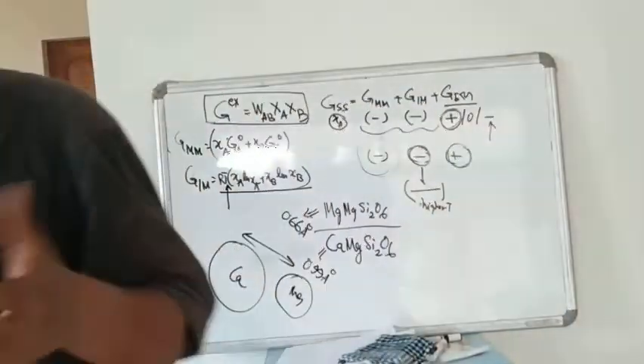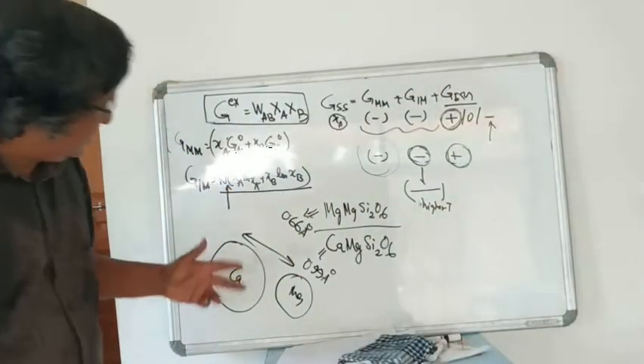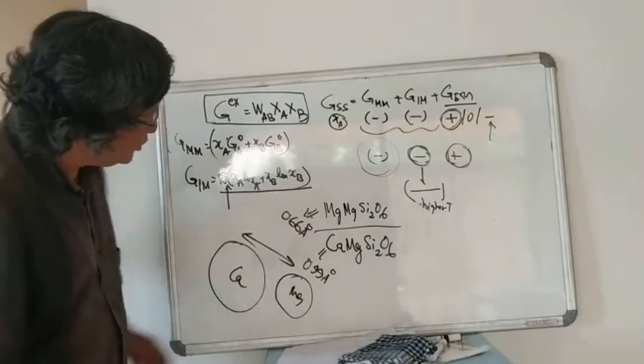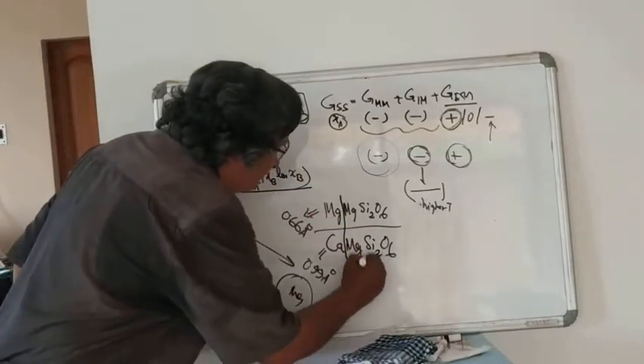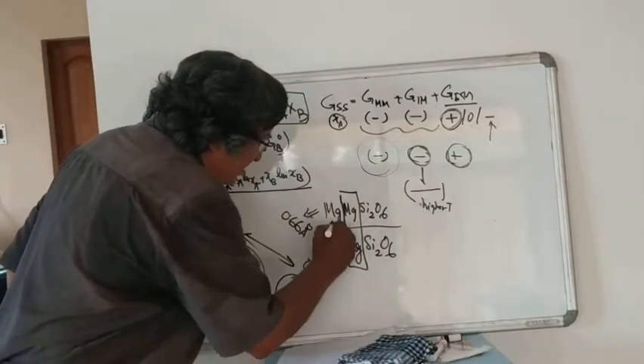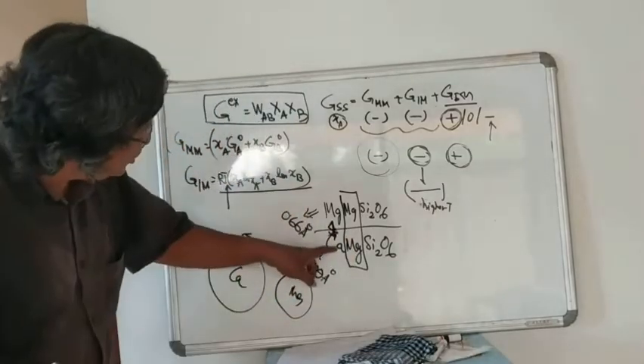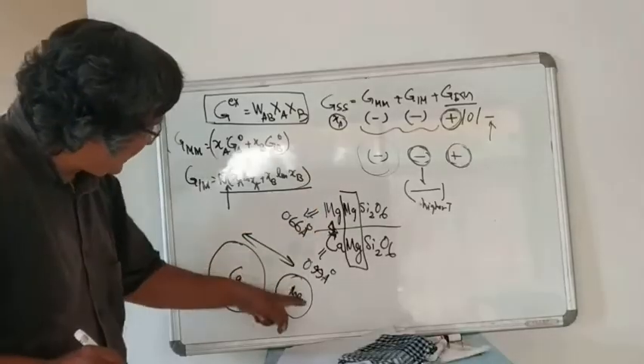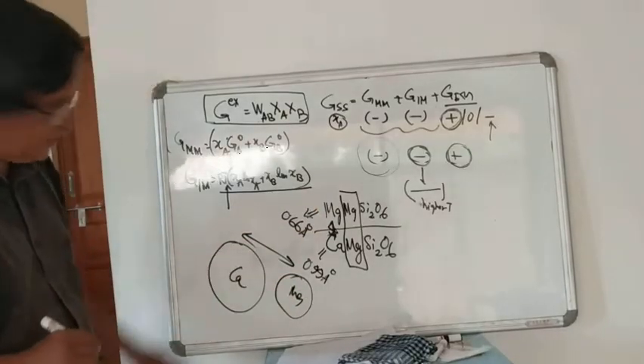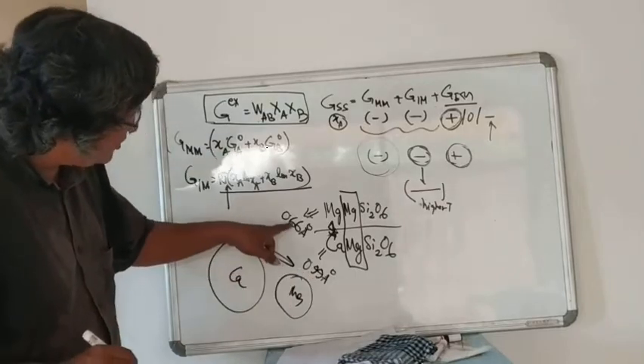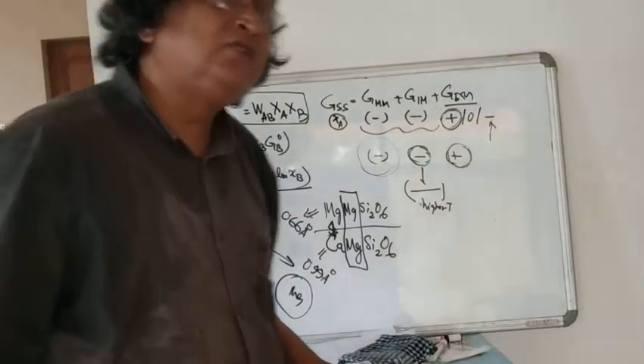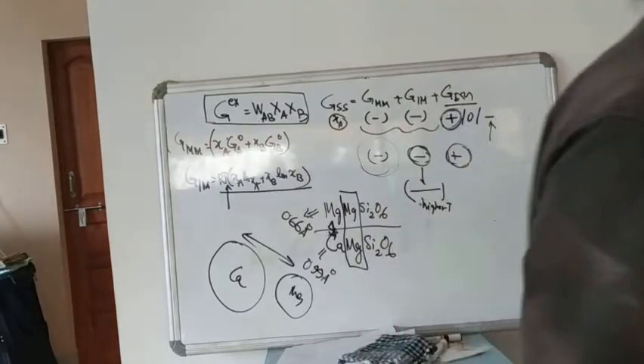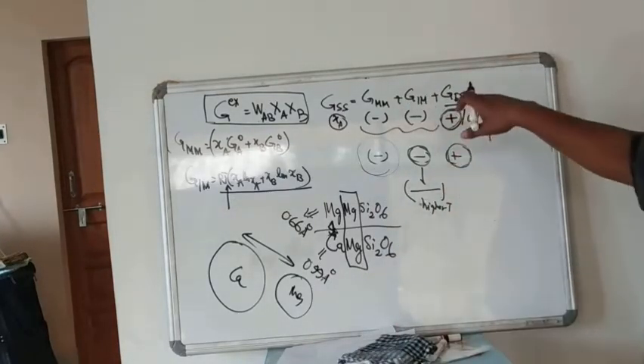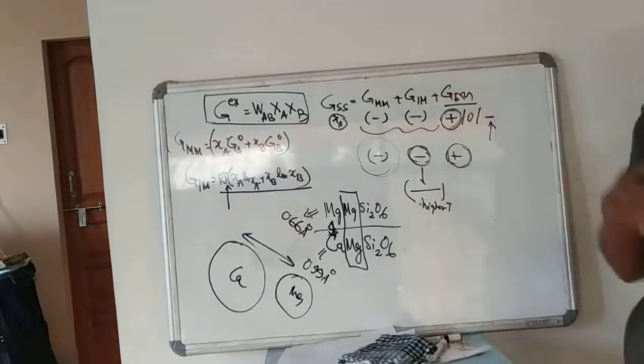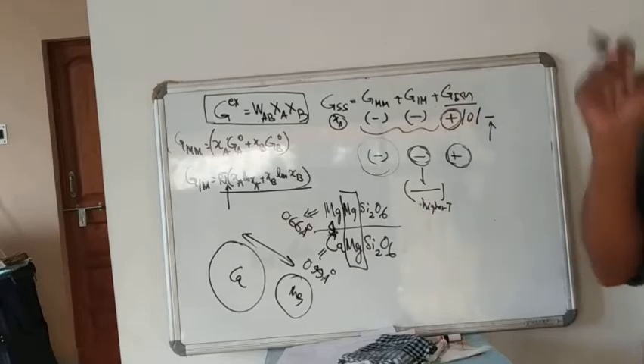But what I am saying is just trying to infer that if you have this type of substitution, there is no problem. But the problem is here. Two same charge cations, very large difference in ionic radius. 0.99 angstrom, 0.66 angstrom, 1/3 less. So this will cause WAB values to be very high. So the chances are you will get exsolution.